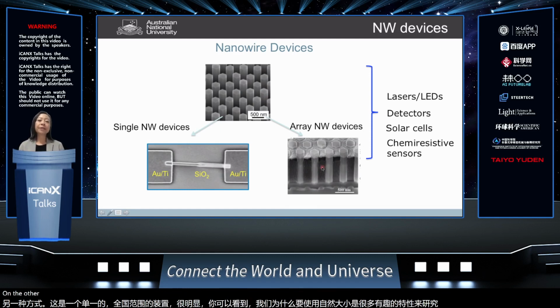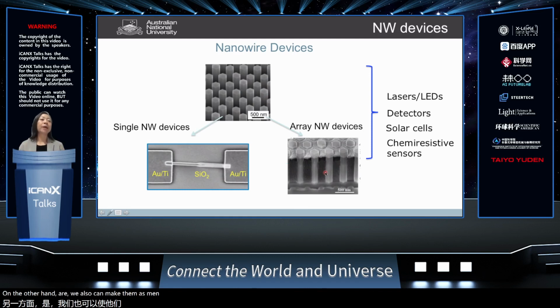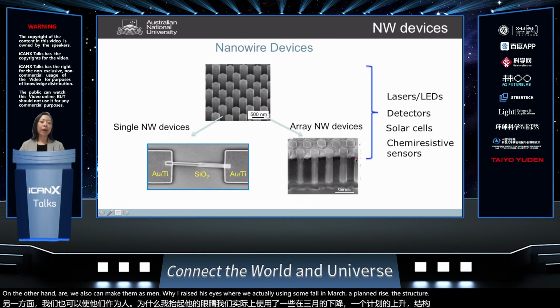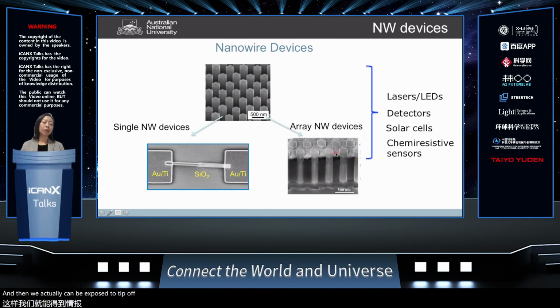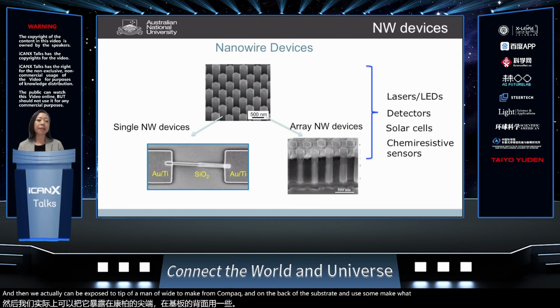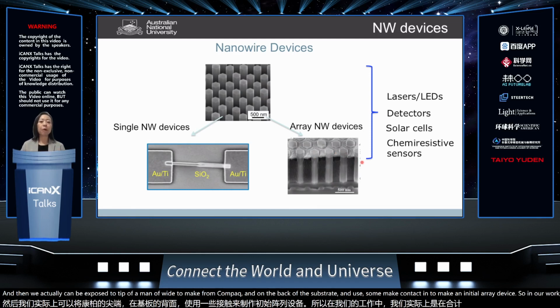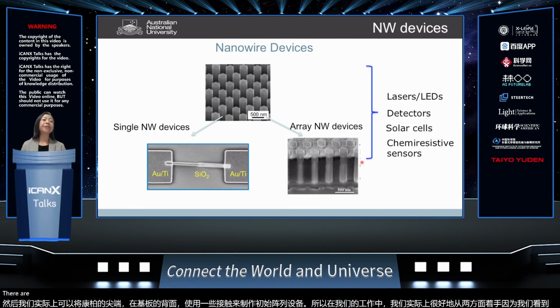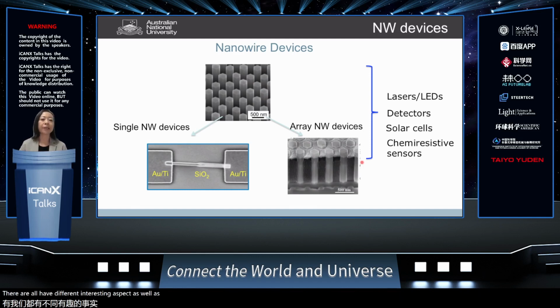On the other hand, we also can make them as a nanowire array device, where we use some polymer to planarize the structure. And then we can expose the tip of the nanowires to make a top contact. And on the back of the substrate, we can make a bottom contact and make them into an array device. So in our group, we work on both because we see they all have different interesting aspects as well as applications. So my talk today will mainly be about arrays, but I'll give a very quick overview of the work we have also done in the single nanowire space.